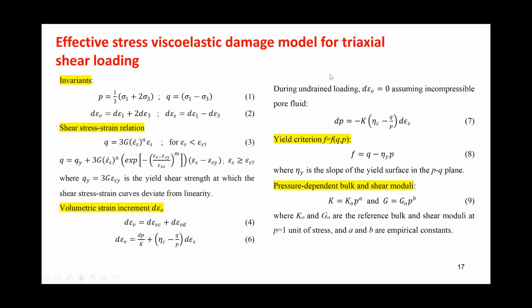Now let's expand the model to an effective stress viscoelastic model for triaxial shear loading. So now we have a full triaxial loading, but also in terms of effective parameters. Effective means total stress minus pore pressure. We use the Cambridge invariants, P and Q, and volumetric strain and shear strain. The elastic stress-strain relation is given by the elastic modulus 3G, and as before, that could be viscoelastic with a static component and a rate-dependent component.